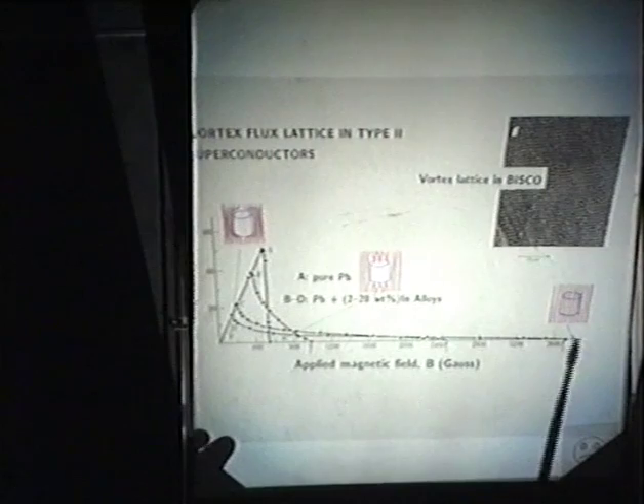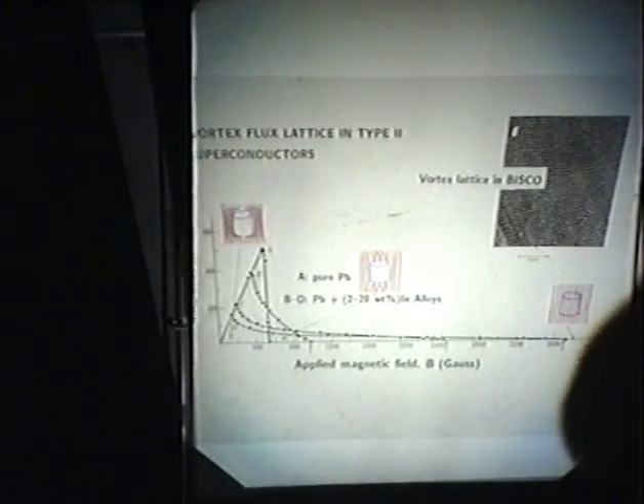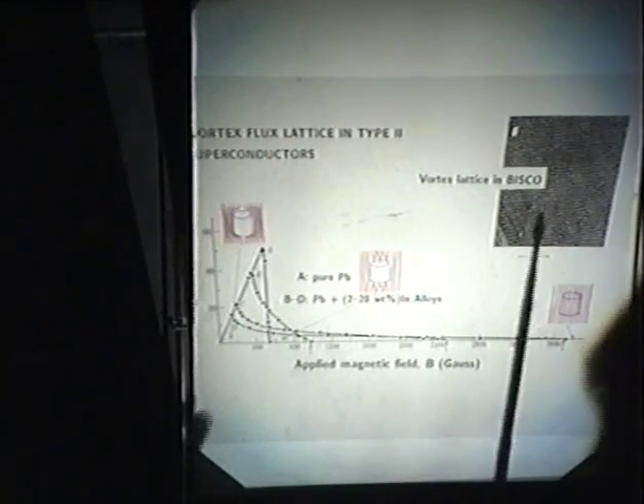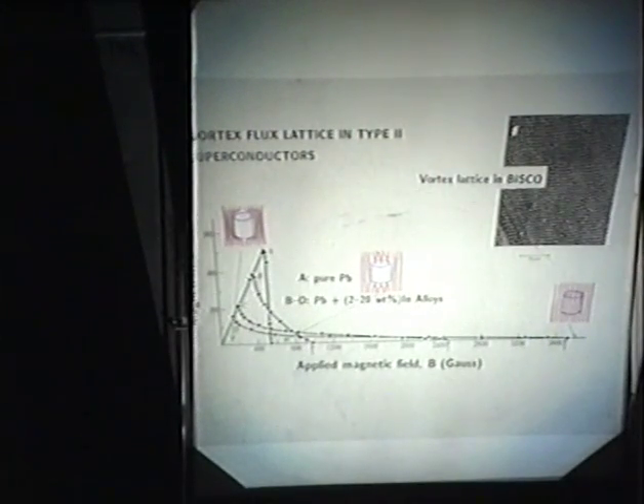And so these curves here, A, B, C, D, are for lead with increasingly higher contamination of indium. And you can see that in the alloy D here, the vortex state exists way up to 3.5 kilogauss before the vortices coalesce and let the field in, and it turns into a normal material again, which is getting up there, getting to be quite respectable.